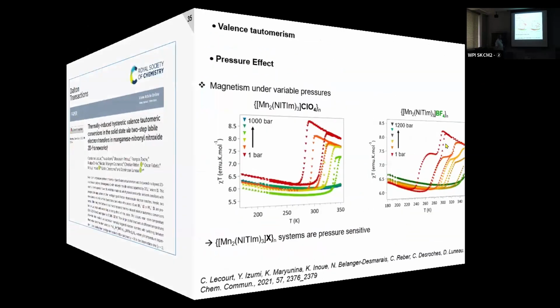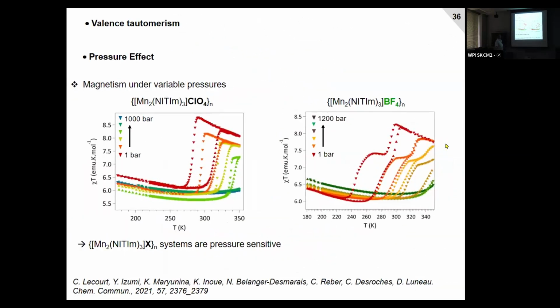Then this was done in Hiroshima by Constance, Yuta, and Selena. So she studied the effect of pressure on this compound. When you study the effect of pressure, you see that when you increase the pressure, the transition is moved to higher temperature, which is normal because you increase the pressure.